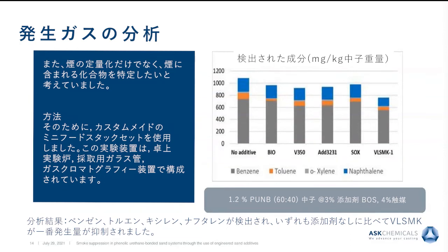So we are excited to show that in the same fashion as the smoke suppression, we are able to reduce some of these emissions with the engineered blend VLSMK-1. Again, here is ASK additive that we had, the Beno Ultra 350. It is an additive we currently use for steel applications. It's commercial. We had 2 more commercial additives here and a typical black iron oxide, just to illustrate where we are with respect to typical additives.